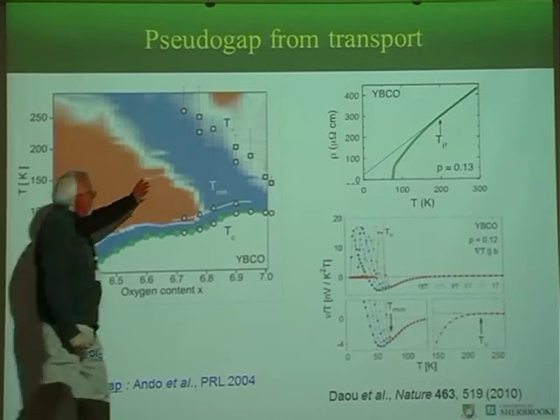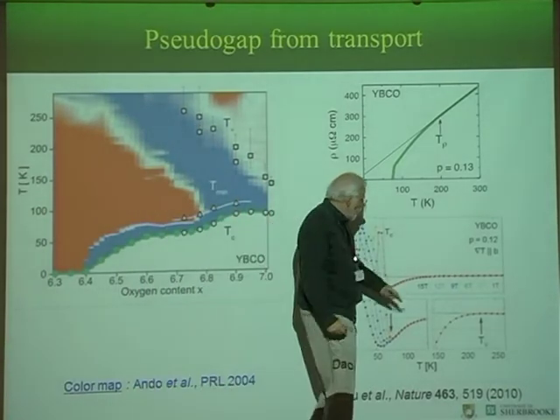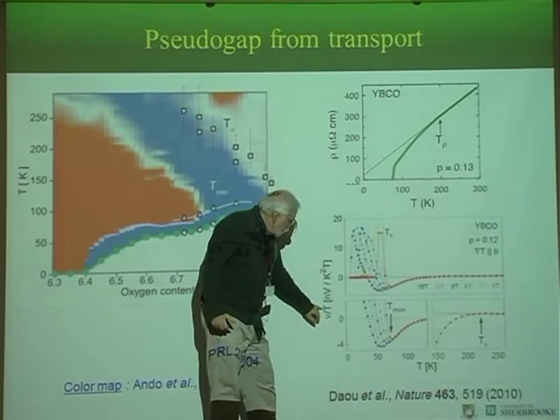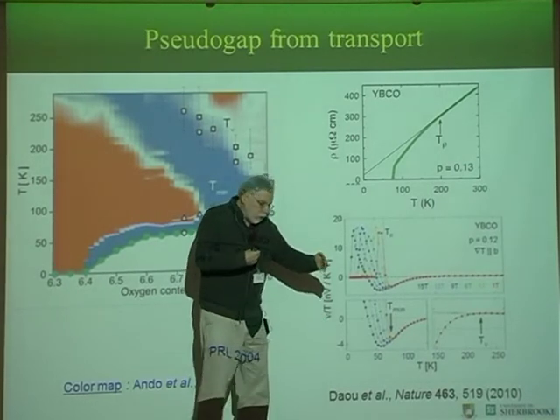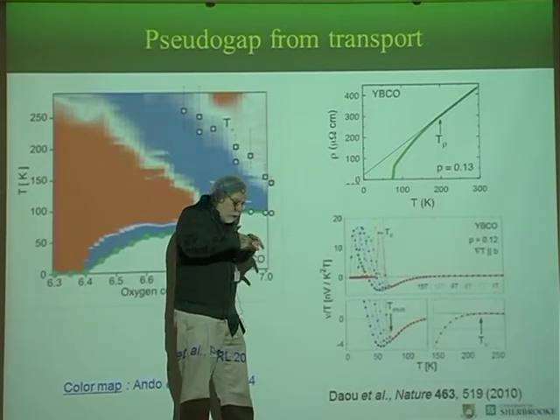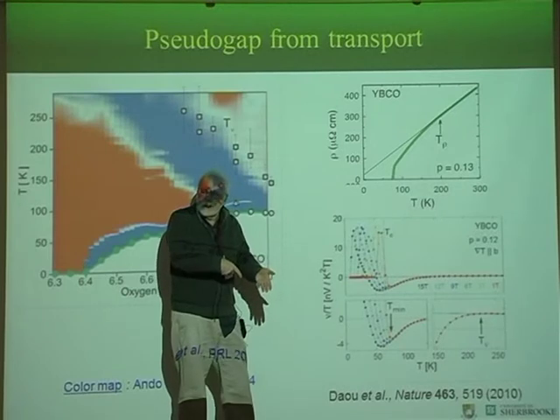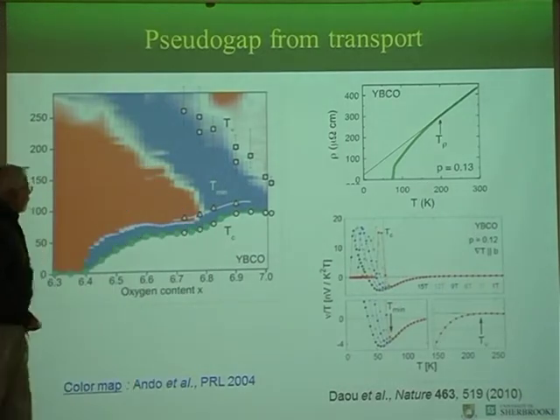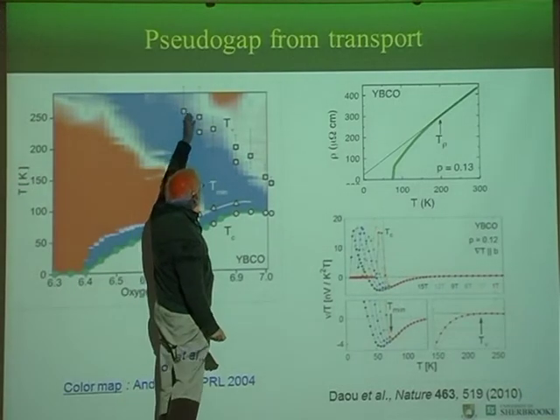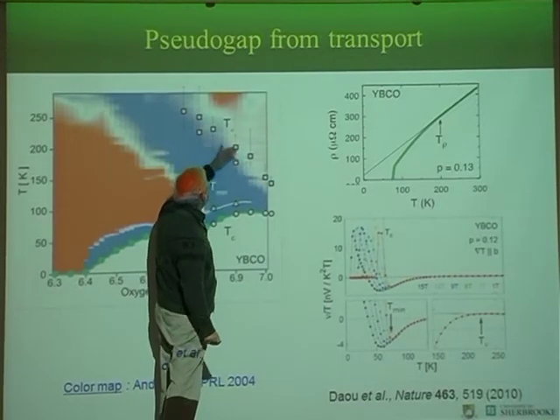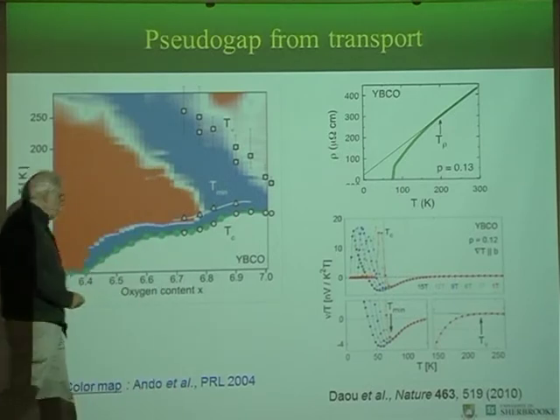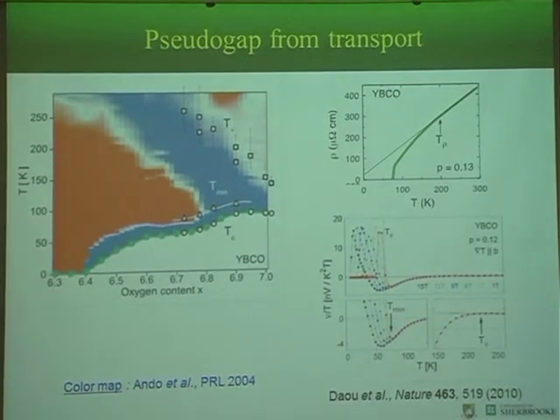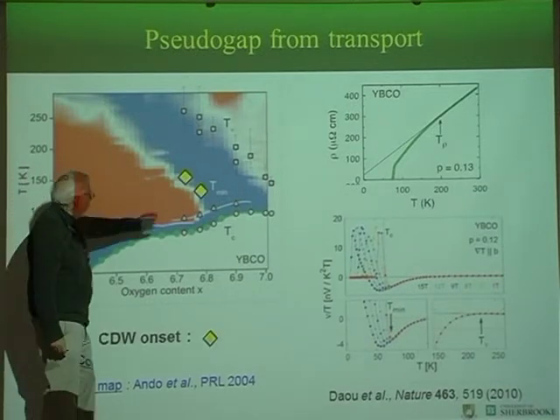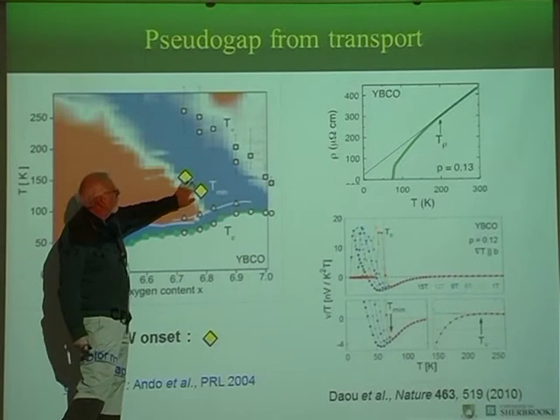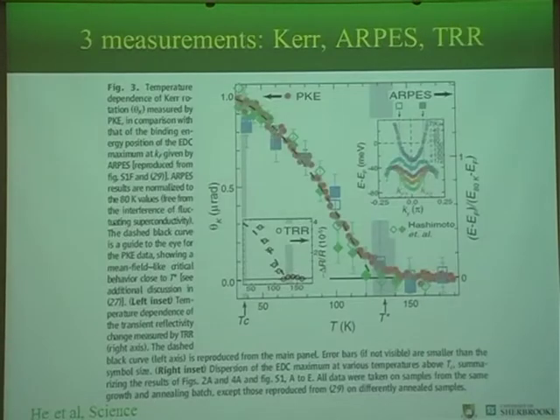And this is where you would see deviation from linearity in the Nernst coefficient divided by temperature. So in the Nernst measurement, what you do is you put a temperature gradient, and you measure the transverse voltage in the presence of a magnetic field. So it's sort of a Hall effect induced by thermal motion. And so you see that the Nernst coefficient occurs basically where the uniform magnetic susceptibility was going down. And the charge density wave transition is here again. It's quite separate from this.